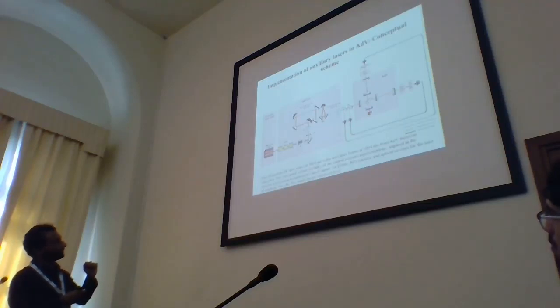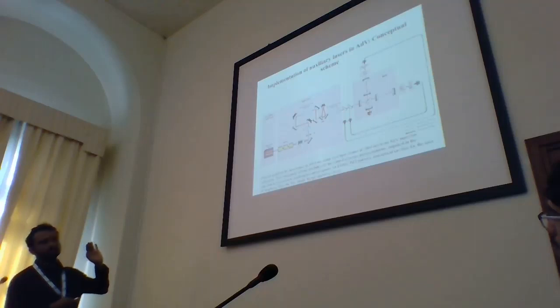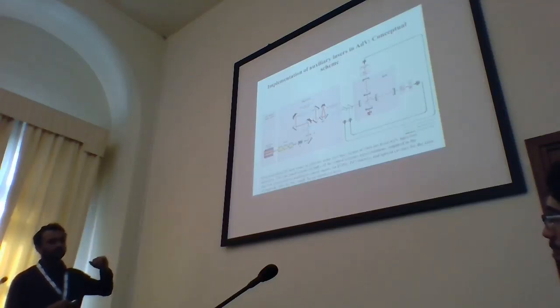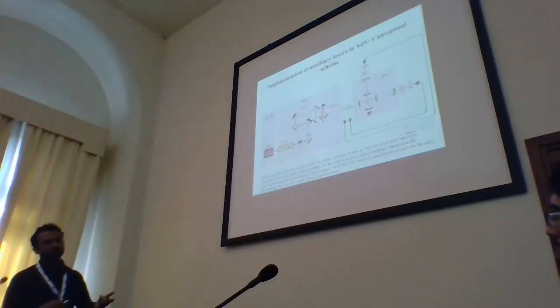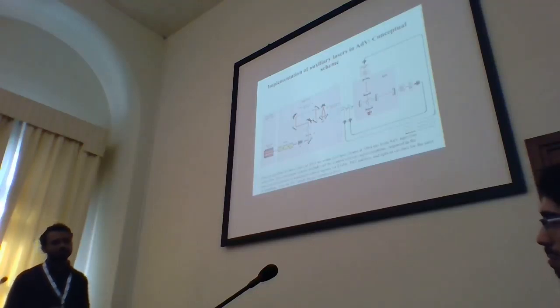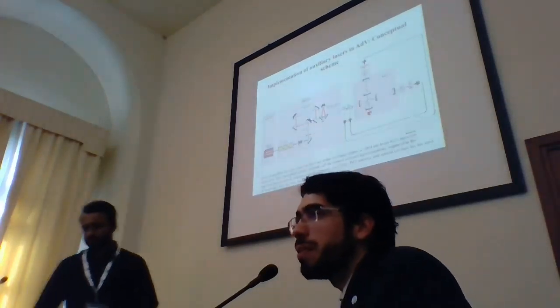In the rest of the interferometer, at different points, you have all these stabilization loops, which allow you to lock different degrees of freedom to their precise accuracy. In our case, this power stabilization loop will be local, and it will only be implemented on the benches and the end test masses. So somehow they are not dependent on any of the systems inside the detector. And to your question about which parameter, it's actually through an acousto-optic modulator that we are trying to control the intensity of the laser field which travels through the system. Yeah. Thank you.